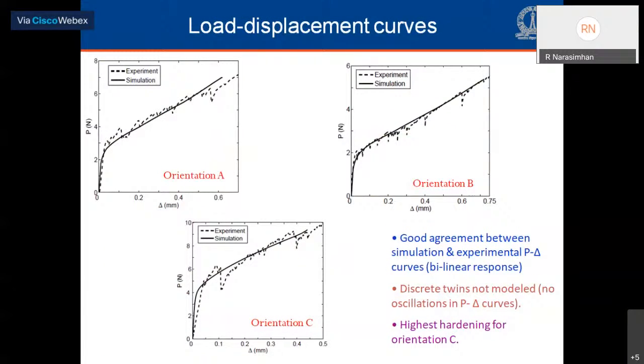These are load displacement plots from the numerical simulations which are compared against the experiments for the 3 orientations. We see a reasonable agreement between the two, and both sets of analysis, experiments as well as simulations, show a bilinear response with very high hardening. And this hardening is associated with twinning, essentially tensile twinning, various mechanisms which are invoked by twinning, like twin-twin intersections, twin-slip intersection, texture hardening. All these result in very large hardening.